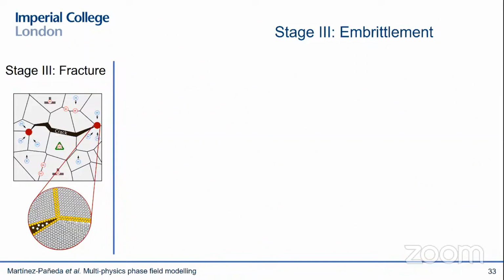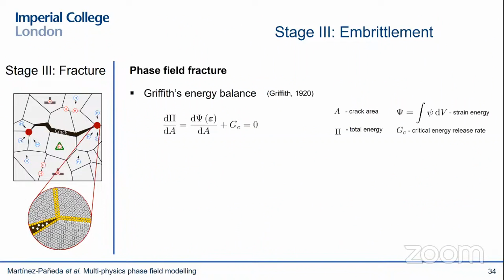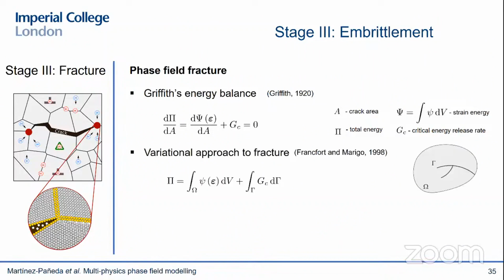energy balance. So those of you that have studied fracture mechanics will remember that Griffith, the father of the field, postulated that a crack will grow whenever the energy stored in the solid was sufficiently large to overcome the energy required to create new surfaces. So we express this, I would say, balance of energy in a variational form. And if you're able to minimize this functional, then you're able to predict the evolution of cracks just as an interplay between the fracture energy and the stored energy in the solid.